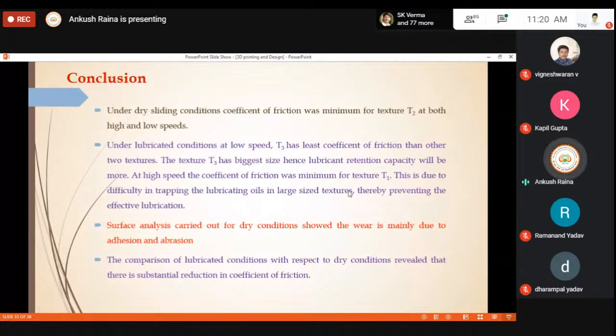And the surface analysis carried out for dry testing showed that wear is mainly due to adhesion and abrasion. You can see that the wear was mainly due to the ploughing effect in all those SEM images which have been shown to you. And again, the comparison which was carried out for dry and lubricated conditions revealed that the lubrication conditions have a substantial effect on reducing the coefficient of friction in all these cases.